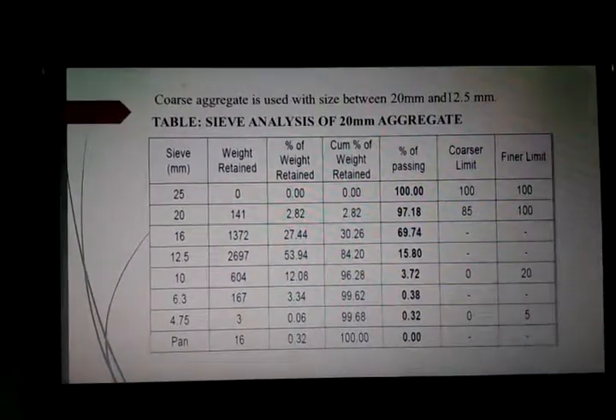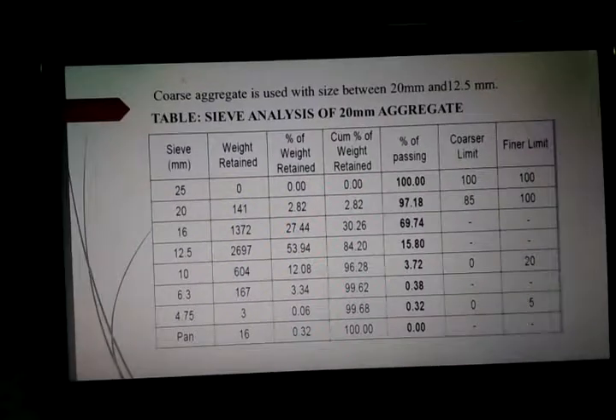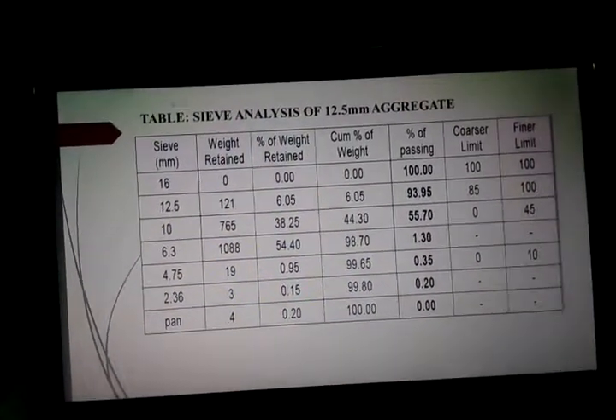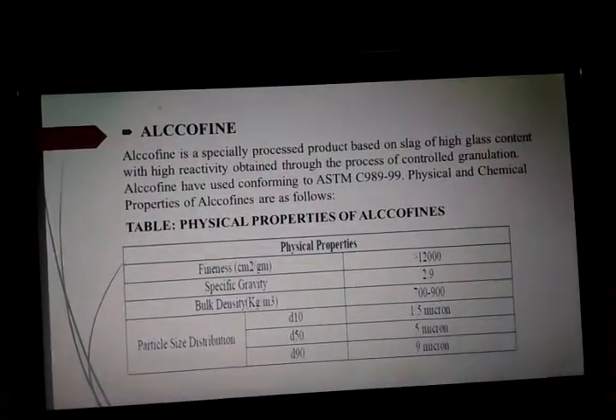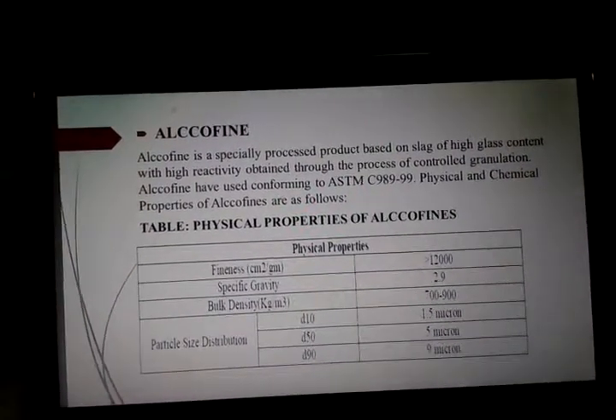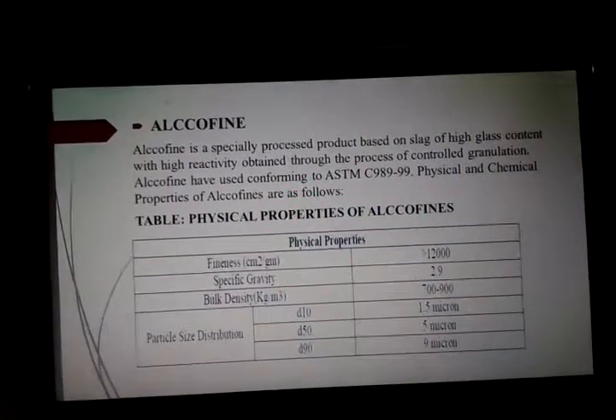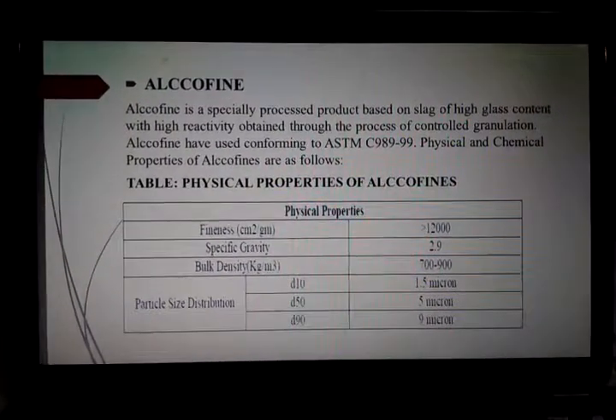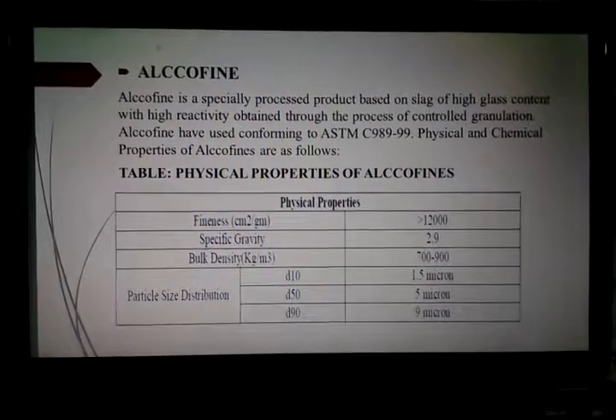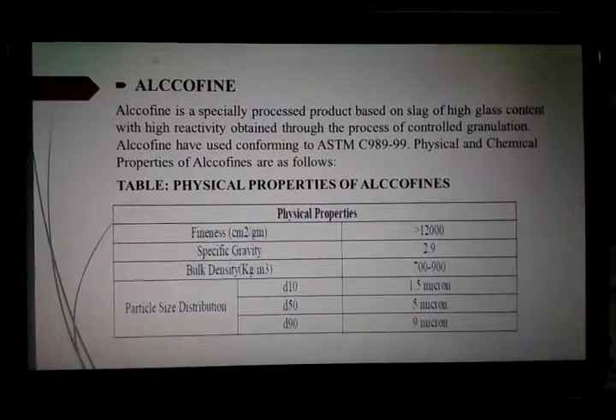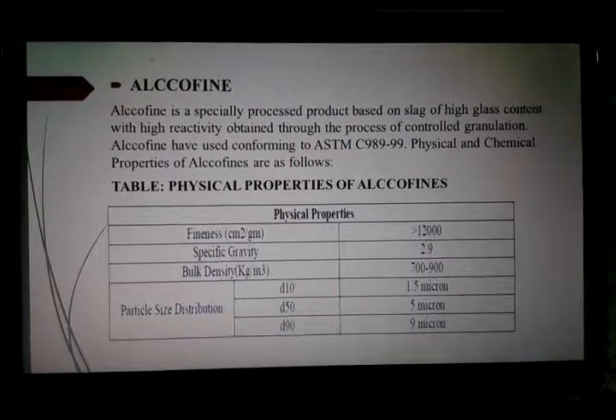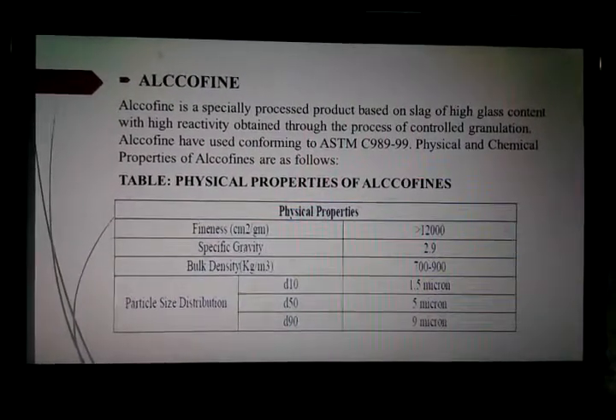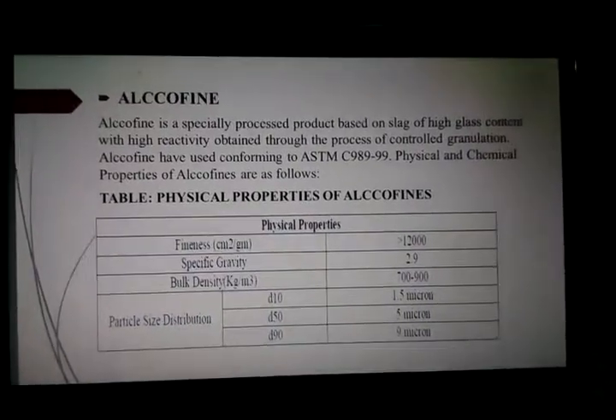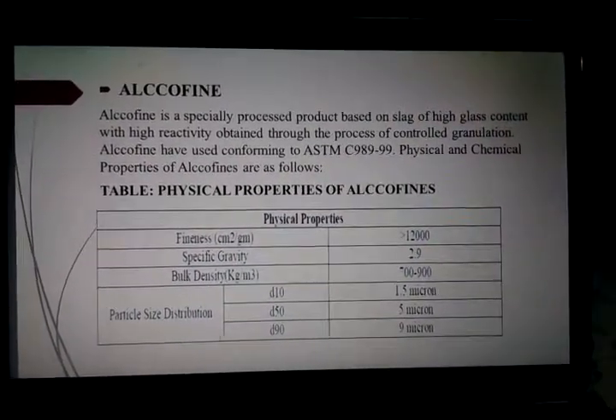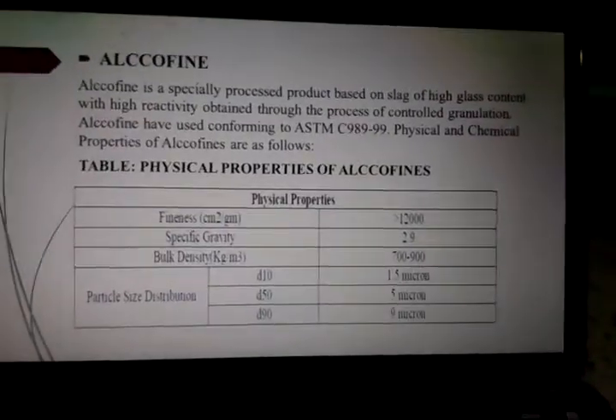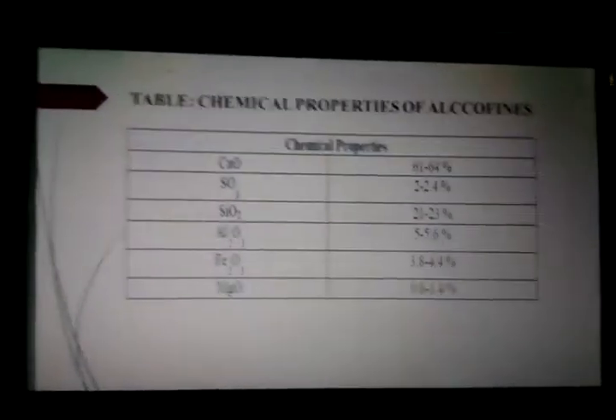Sieve analysis of 20 mm aggregate is as given, and the finer limit is as mentioned. The sieve analysis of 12.5 mm aggregate is also given here. Alccofine. Alccofine is a specially processed product based on slag of high glass content with high reactivity, obtained through the process of controlled granulation. The alccofine has been used conforming to ASTM C989-99. Physical and chemical properties of alccofine are as shown. Fineness, specific gravity and bulk density are given here. Fineness is greater than 12,000 cm square per gram. Specific gravity is 2.9. Bulk density is 700 to 900 kg per meter cube.